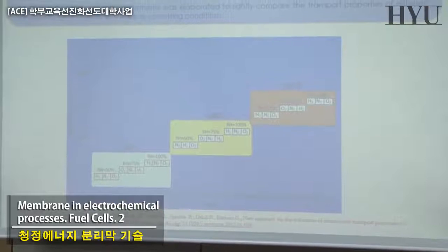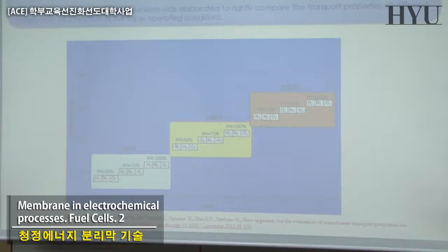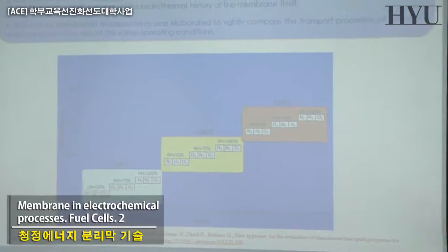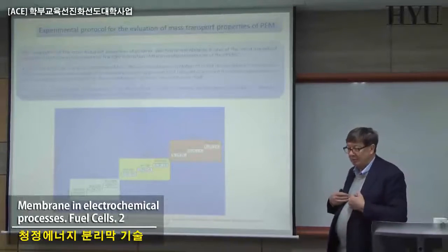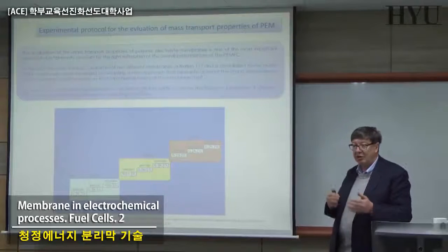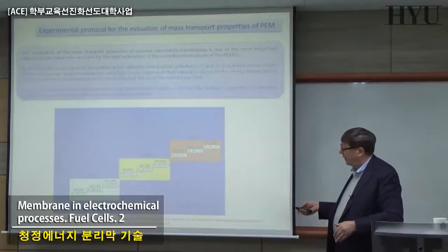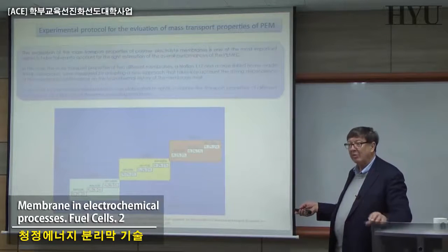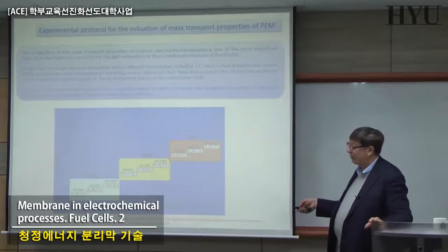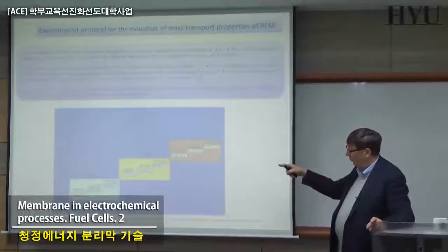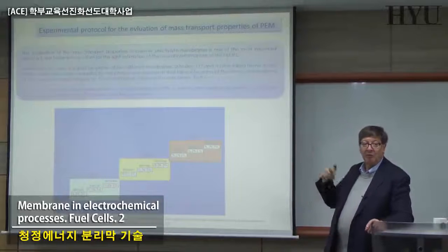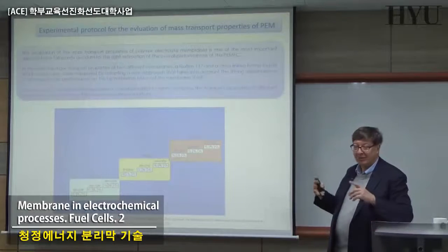At each temperature, you have a different level of composition, different gases with a certain relative humidity, 50%, 75%, 100%, etc., just to try to minimize possible differences between the same data that you obtain on one kind of membrane in one country and on another kind of membrane in another country. And that seems to be a minor problem, but it is not minor at all, because the system is much more complicated than expected. The efficiency we are measuring is only F2, F4, but there are 7 fluxes that can have some effect.